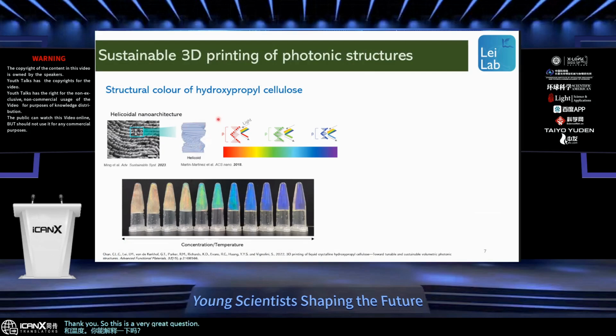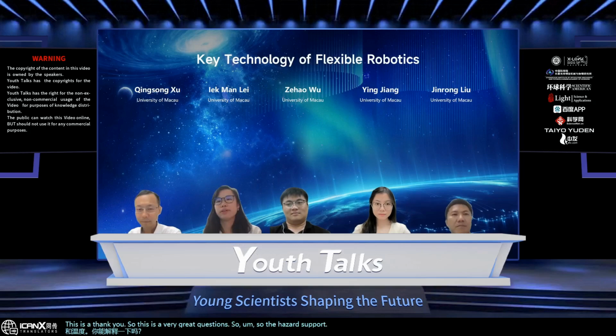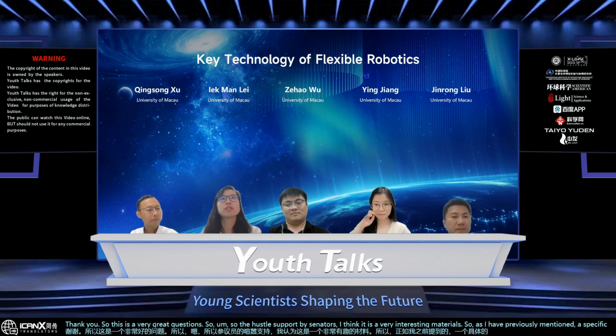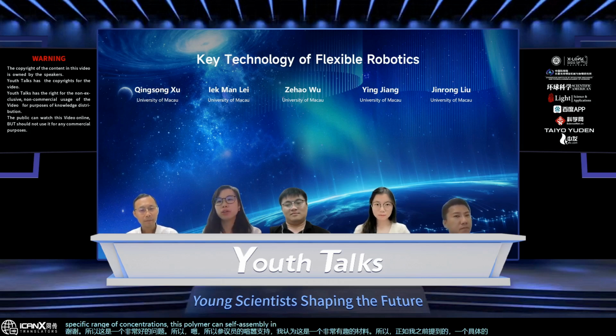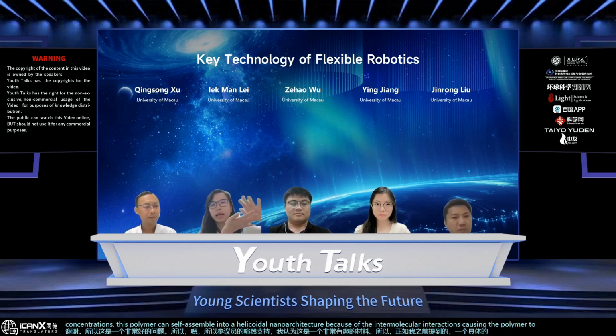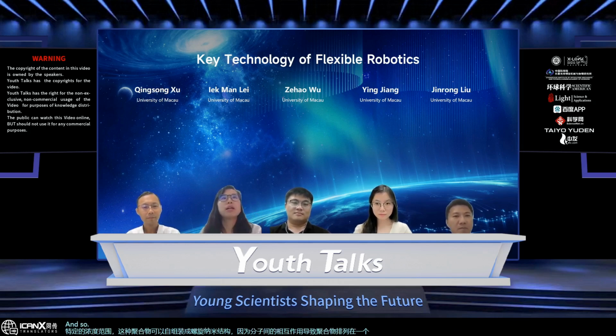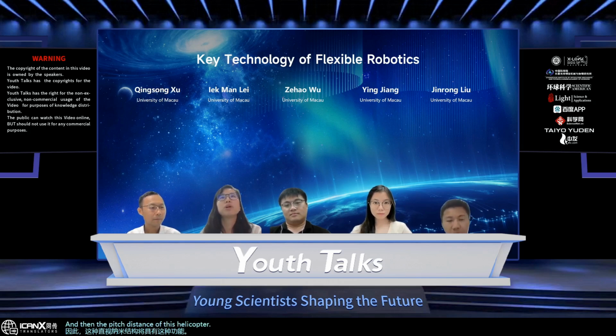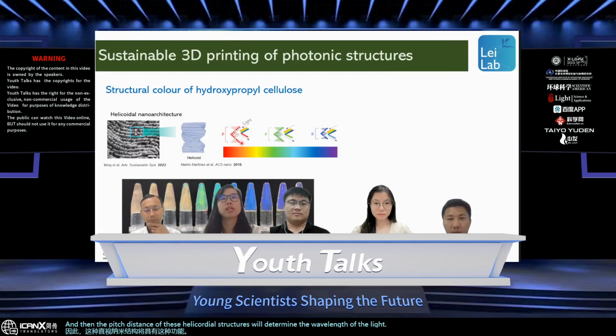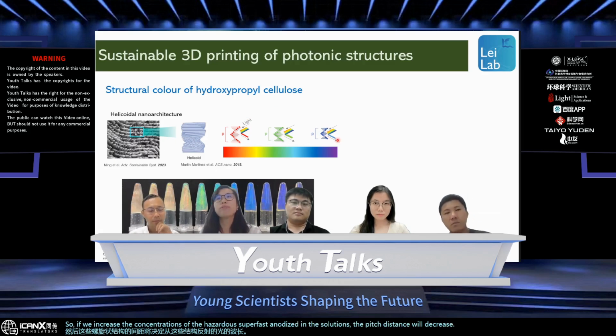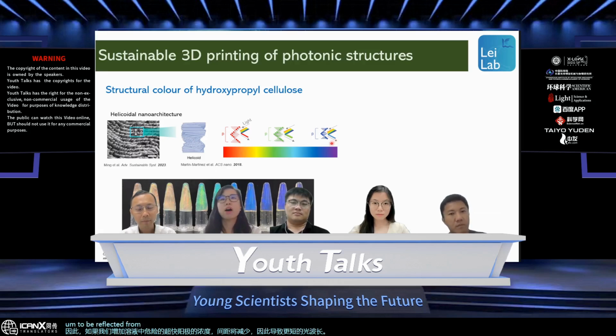Thank you, this is a very great question. Hydroxypropyl cellulose is, I think, a very interesting material. As I have previously mentioned, at a specific range of concentrations, this polymer can self-assemble into helicoidal nanoarchitectures because of intermolecular interactions. The pitch distance of these helicoidal structures will determine the wavelength of the light reflecting from them. If we increase the concentration of hydroxypropyl cellulose in the solution, the pitch distance will decrease, causing a shorter wavelength of light to be reflected.